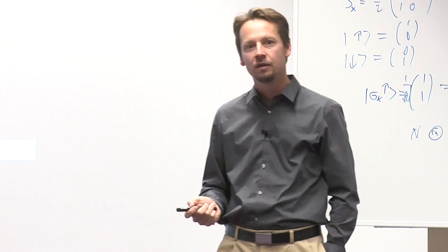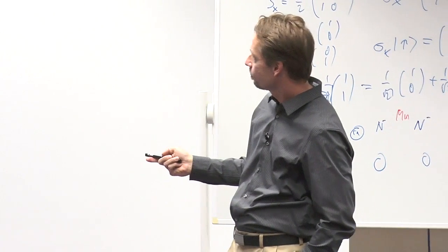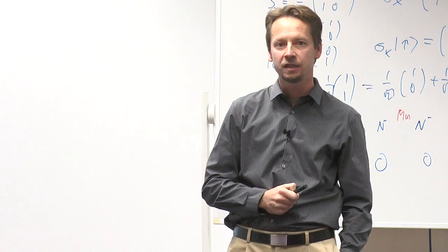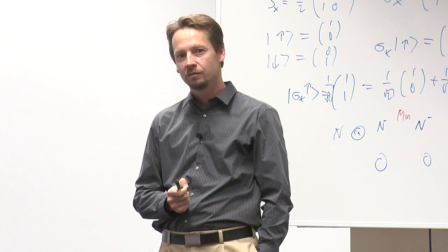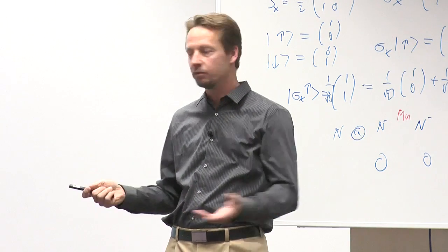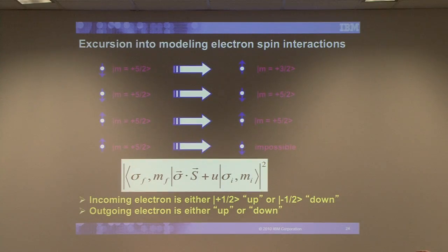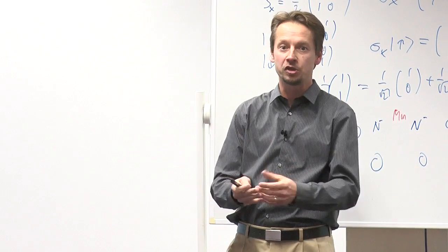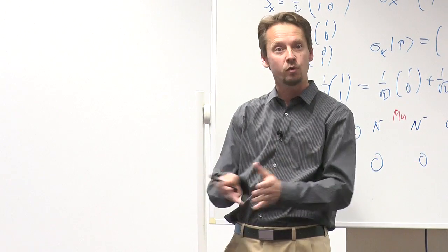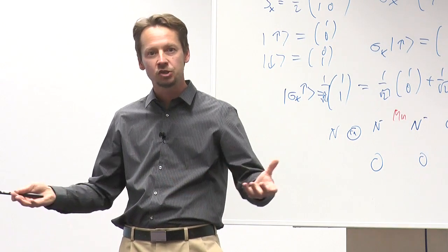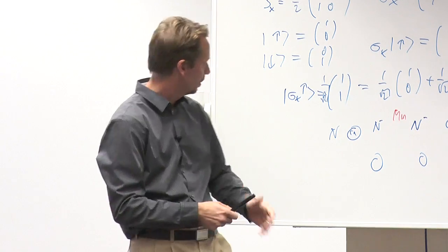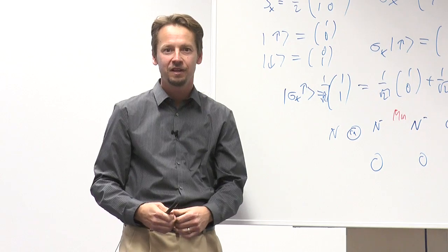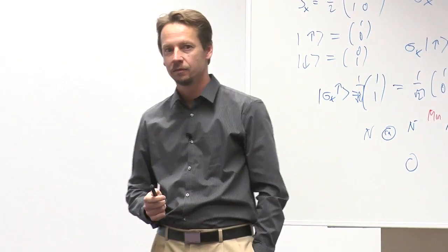Is it zero field or what is it? You fit it probably to something. Yes, so we fit, this holds at any magnetic field. And we basically fit it, for example, this U parameter is a single parameter, one number, basically a real number. And we fit this to a certain set of measurements, for example, as a function of magnetic field. But we want this parameter to be constant, independent. It should be a parameter that only depends on having manganese in this particular configuration. Okay, this means U is fixed, basically. And then everything else should come out of that, basically. Right?